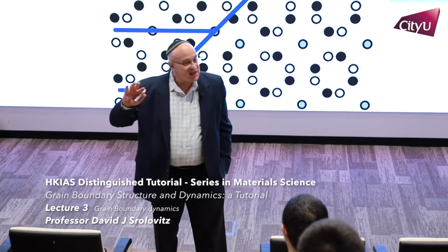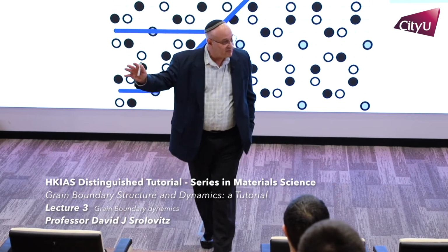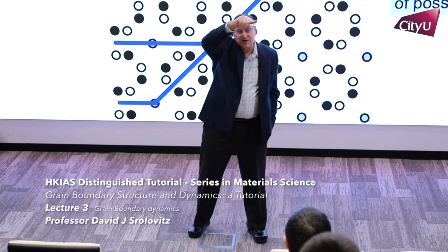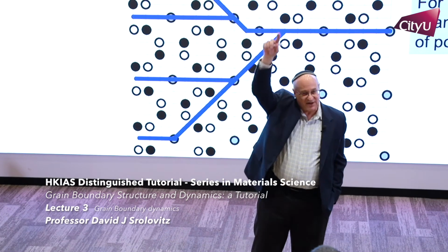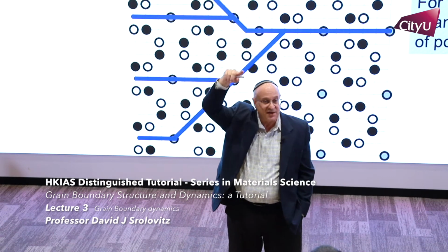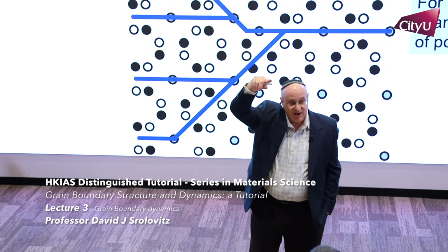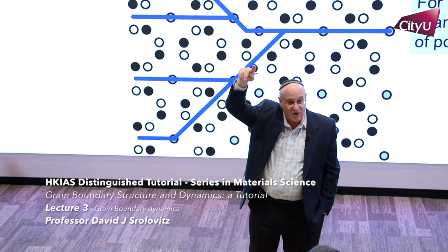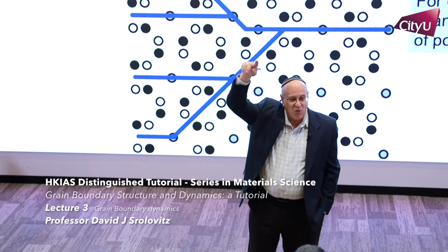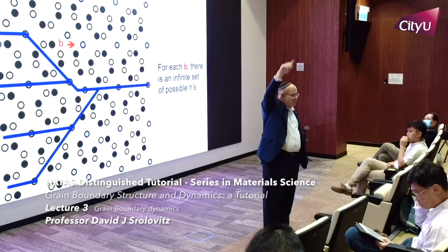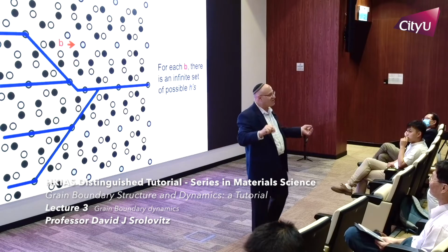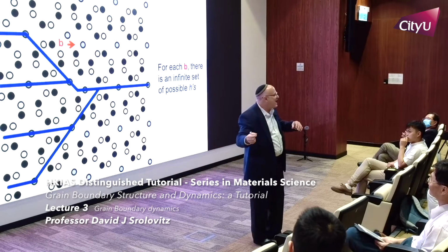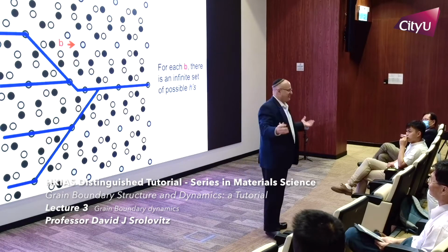And it's just like if I take an FCC crystal. I can take a Burgers vector to be along 1/2 <110>, but I can also choose a translation vector, a Burgers vector, to be <100> or <200> or pick <123>. They're all translation vectors which the crystallography allows, but energies are going to determine which ones actually are important.